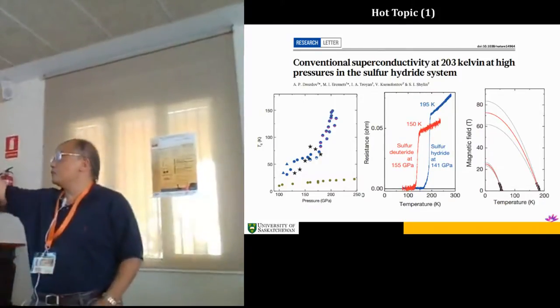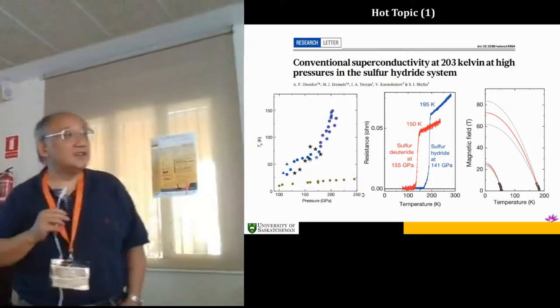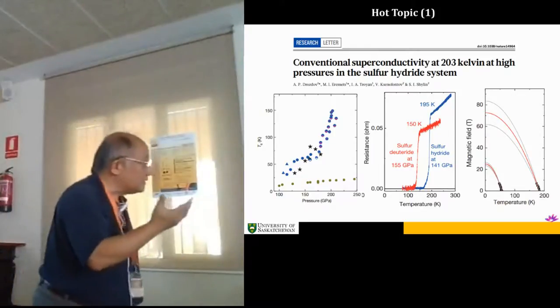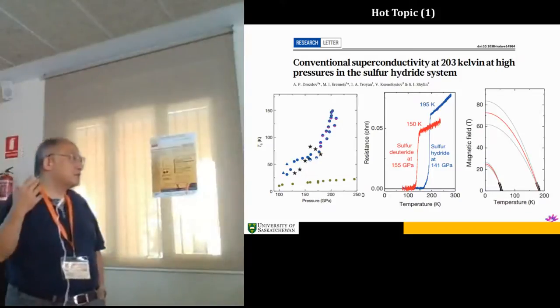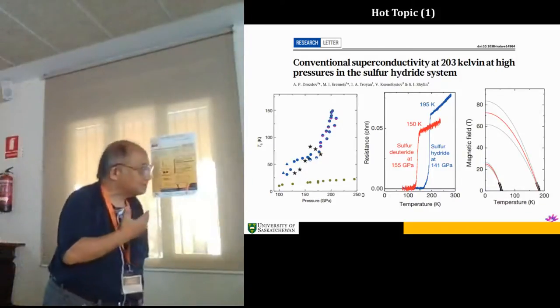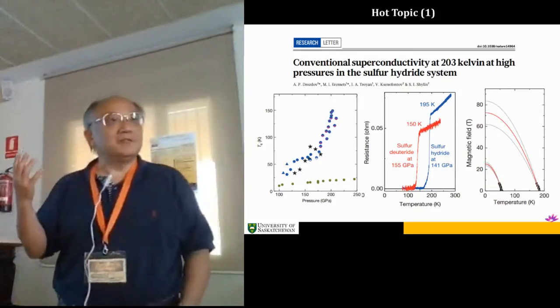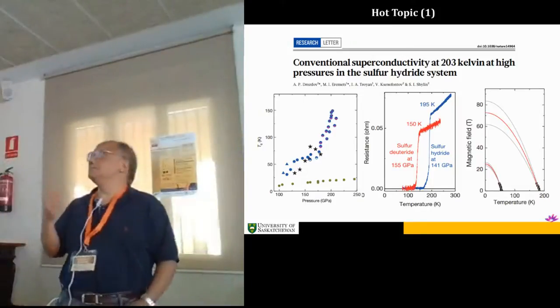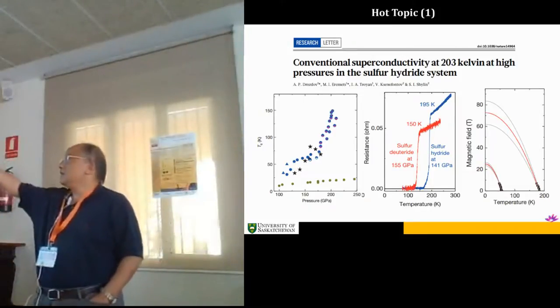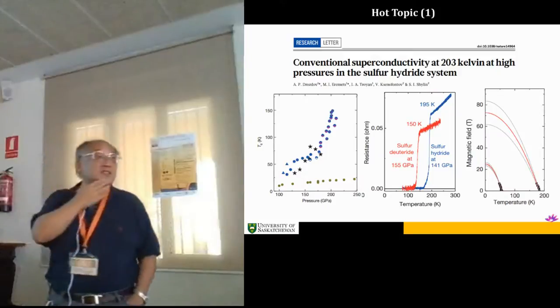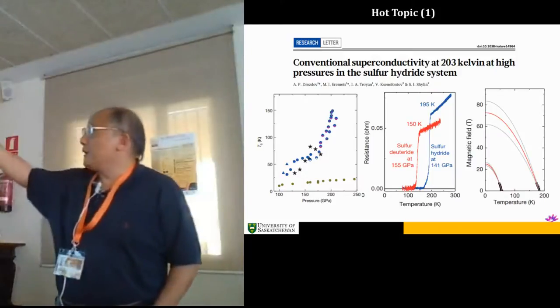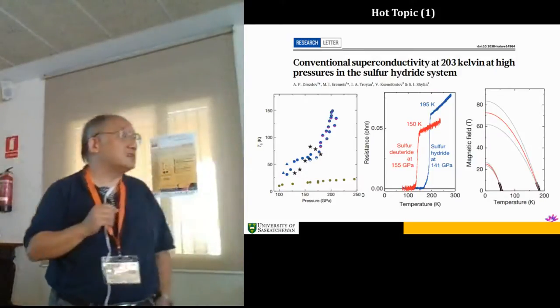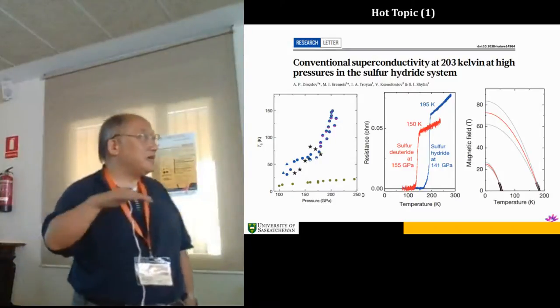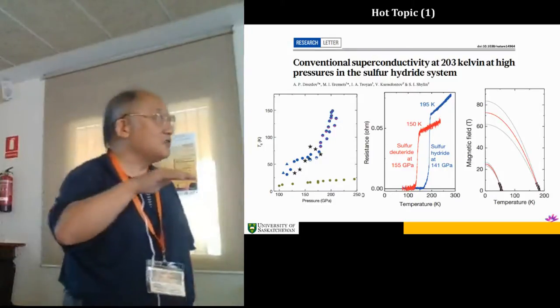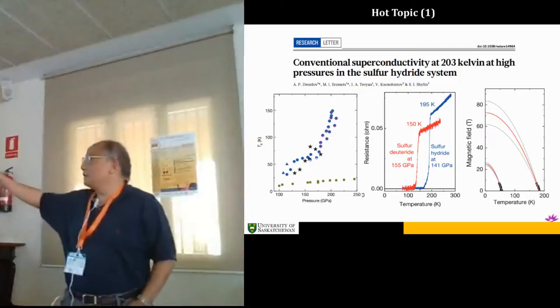One is, of course, the superconductivity of hydrogen sulfide. When you compress it, it reaches 200 Kelvin, dry ice temperature. All right? You can do it at home, dry ice. And this measurement apparently is conventional BCS. That means it's a phonon-mediated process. Now, that's an interesting thing. All right? They have the magnetic measurement.